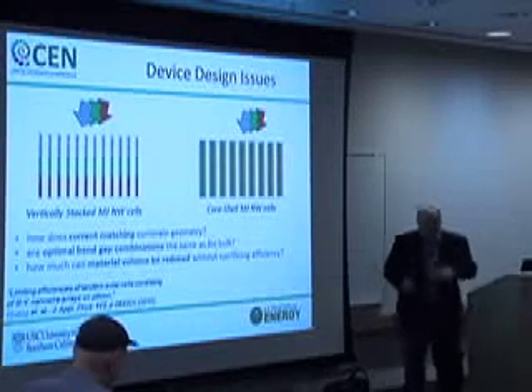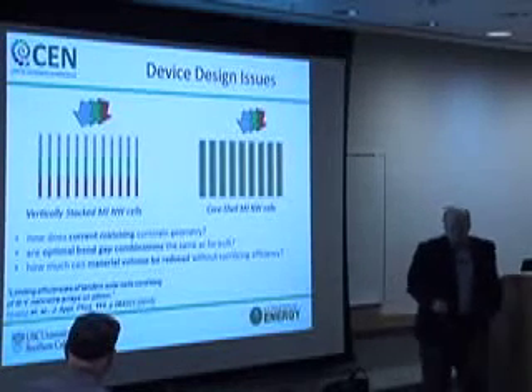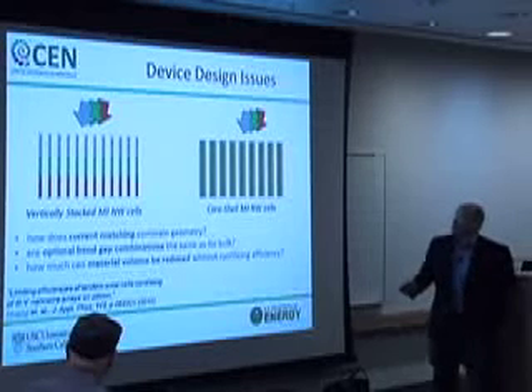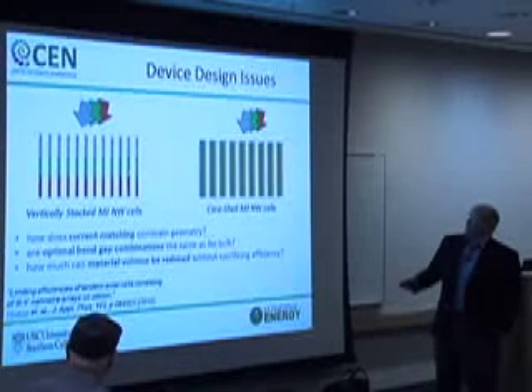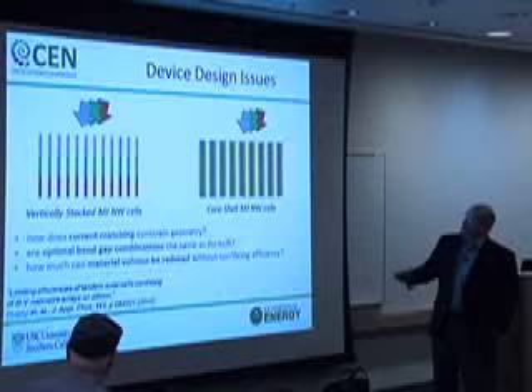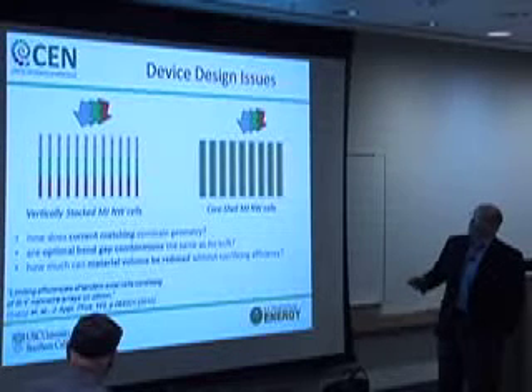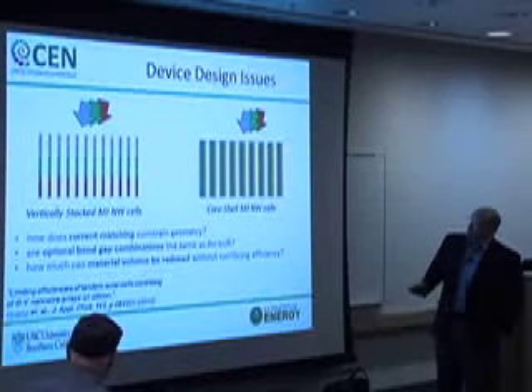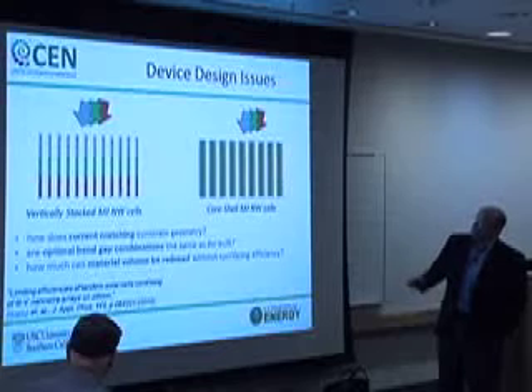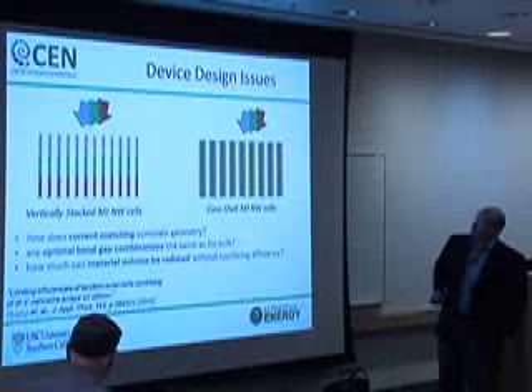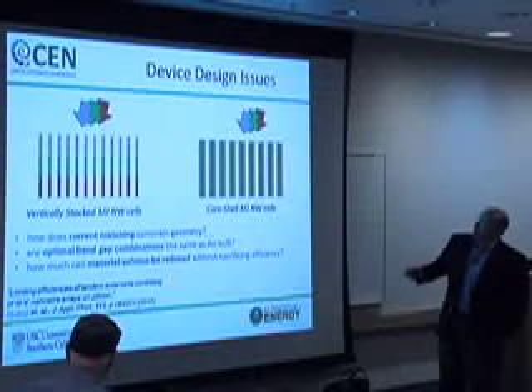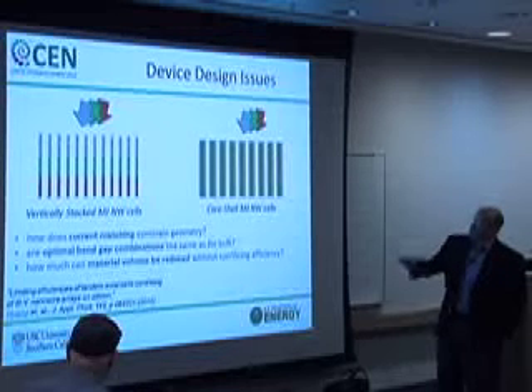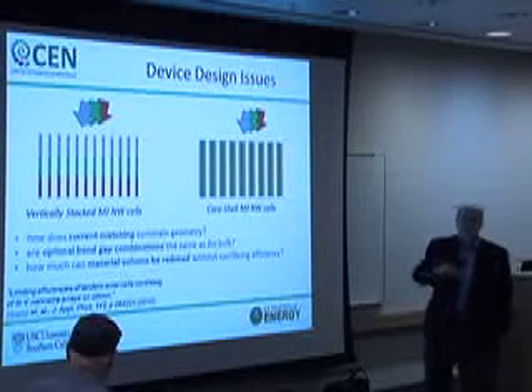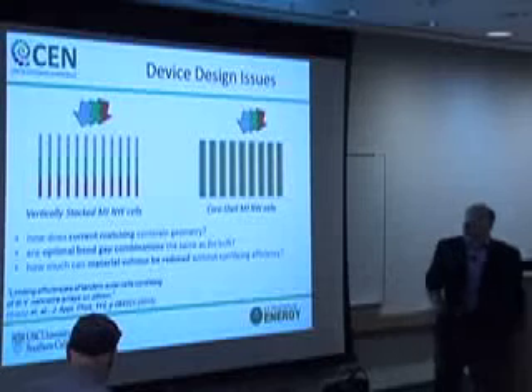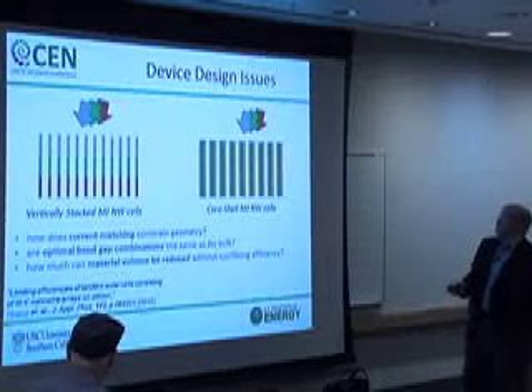Now, when you talk about a multi-junction cell, you have a couple of possibilities. You could stack the materials one on top of the other, and I try to indicate that with the color of the portions of the bar. So the lowest band gap is on the bottom, intermediate and top, like this. And under those circumstances, the light has to pass sequentially through the different cells, much the same as it would in an epitaxial layered structure.